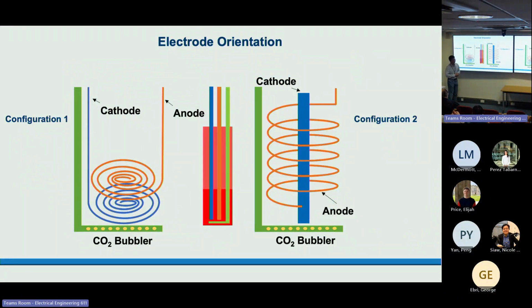So we have two electrode configurations now. Both of them can achieve a uniform electric field in the electrolyte. Firstly, we use two metal wires shaped into spiral discs, and we put them facing each other. We put the anode on the top and the cathode on the bottom. The reason is that oxygen gas will be generated on the anode. If we put the anode at the bottom, the evolving oxygen gas in the form of bubbles may have an influence on the carbon nanotubes produced on the cathode.